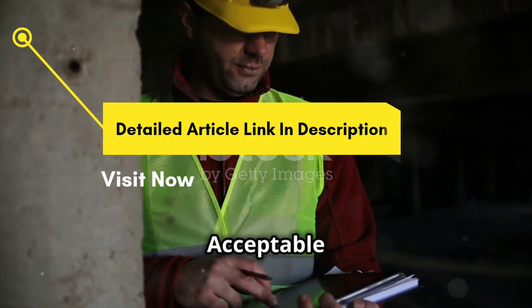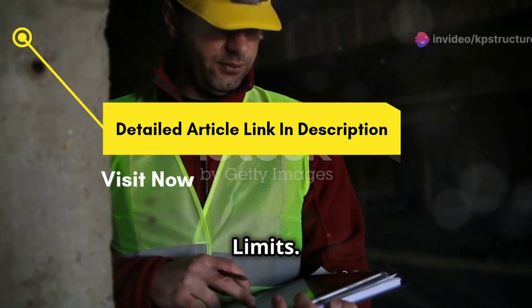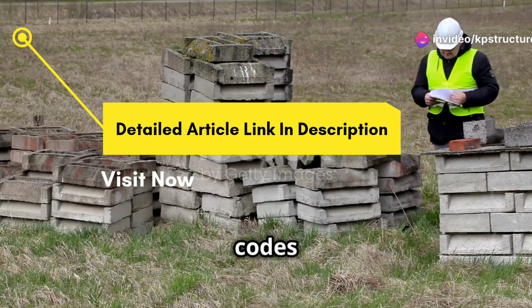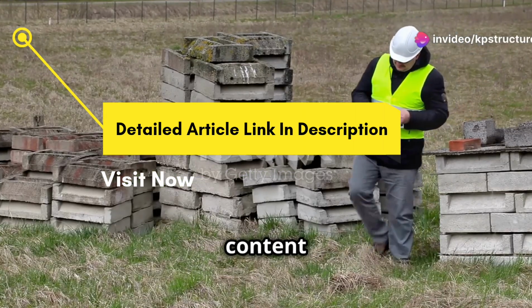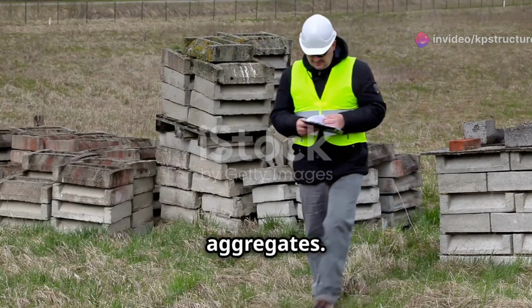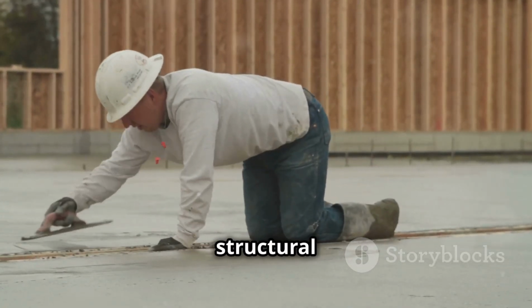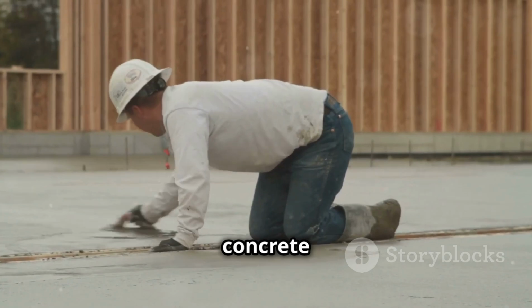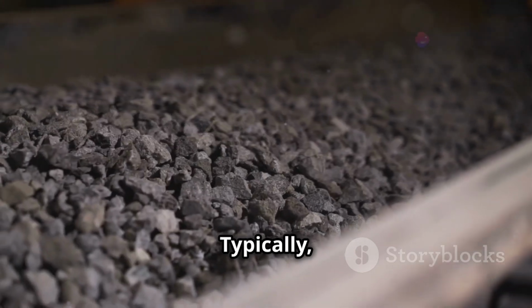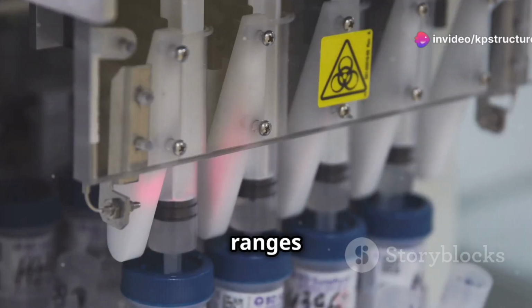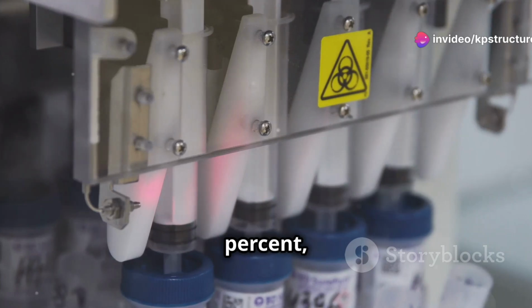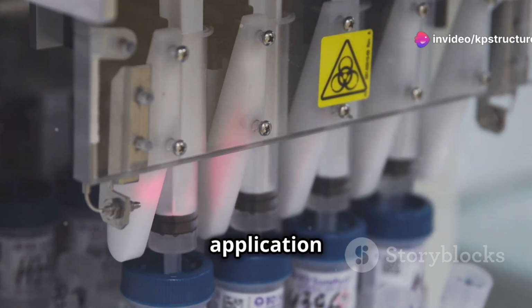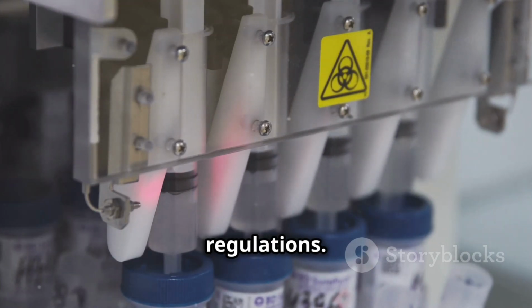Section 5. Acceptable silt content limits. Construction standards and building codes specify acceptable silt content limits in fine aggregates. These limits ensure the structural integrity and longevity of concrete structures. Typically, the acceptable silt content ranges from 3% to 6%, depending on the specific application and regional regulations.